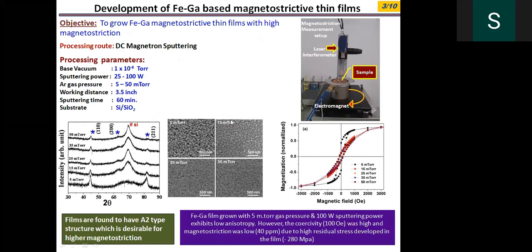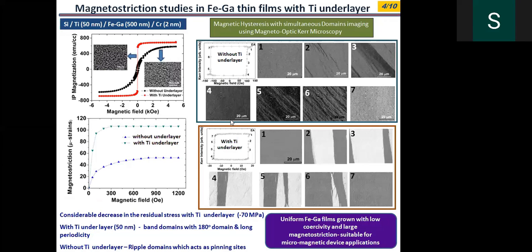To reduce the stresses, what we have done is we have gone for an underlayer deposition. We used titanium as underlayer. When we use titanium as an underlayer, what we observed is the anisotropy is found to be highly in plane, and this is very clearly seen from the magneto-optical microscopy studies. And also when you see the magnetostriction curve, without titanium underlayer, the magnetostriction is found to be low, but with titanium underlayer, there is a considerable improvement in the magnetostriction.